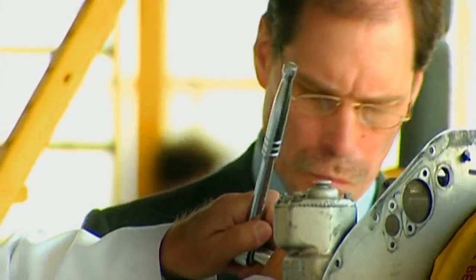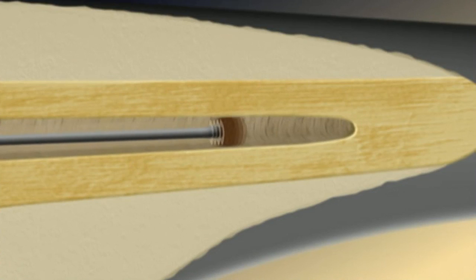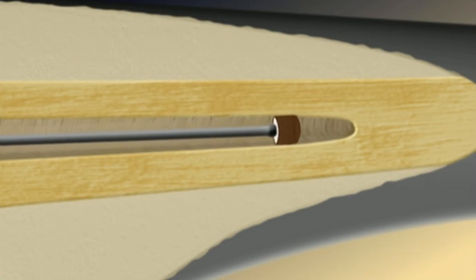When he was examining the propeller blade, Bender had been unable to detect any evidence of corrosion. He then did what he'd been told to do: polish the inside of the blade. He was given a directive to use a repair to blend out the inside of the taper bore. He blended it out, he did an inspection, and the blending that he had done had roughened the surface, so it actually masked the indication of the crack in the subsequent inspection, and the blade was returned to service, where the crack continued to propagate until it ultimately reached critical length and separated.